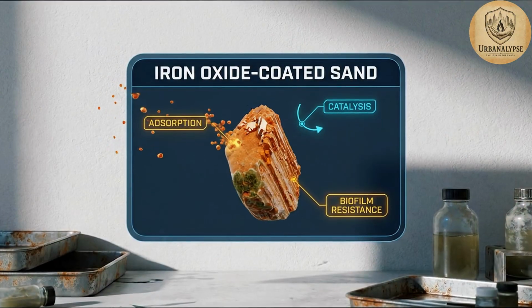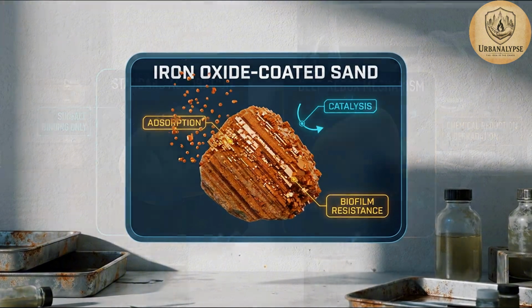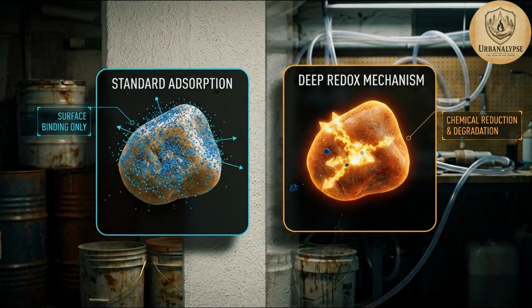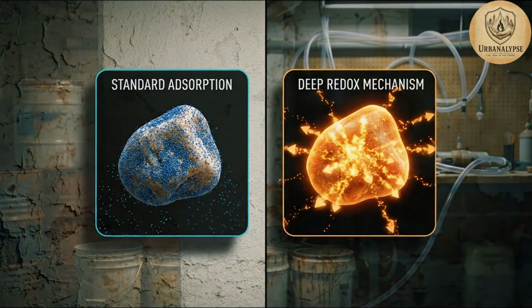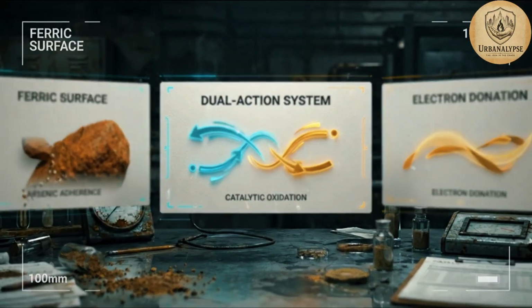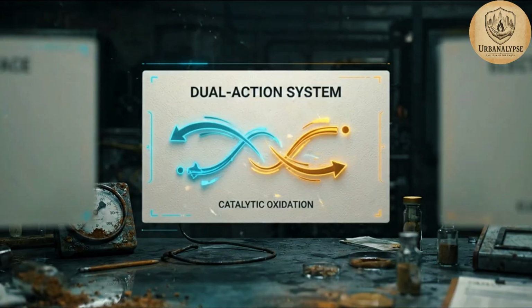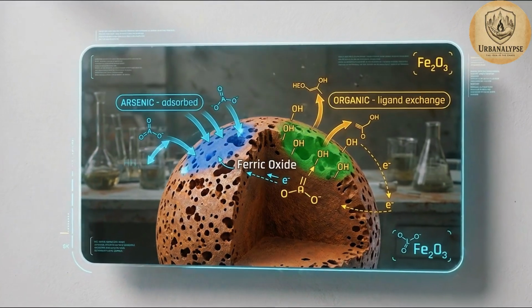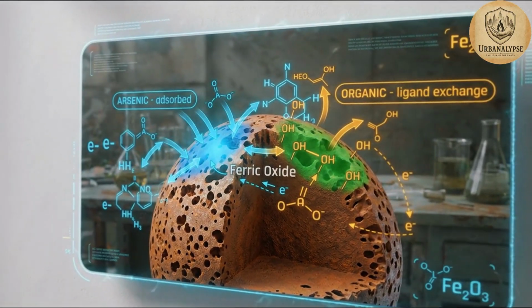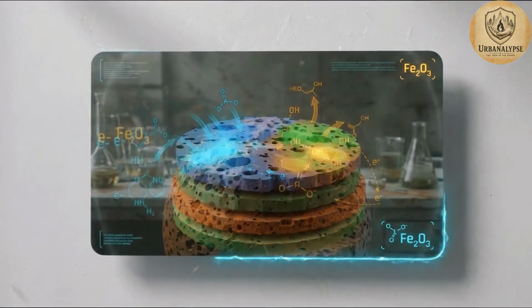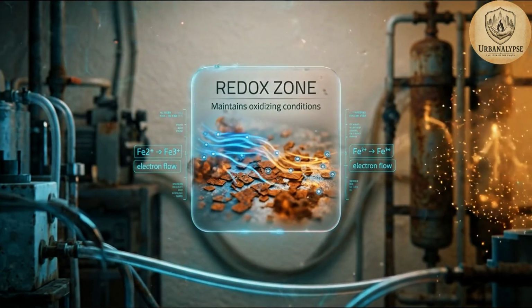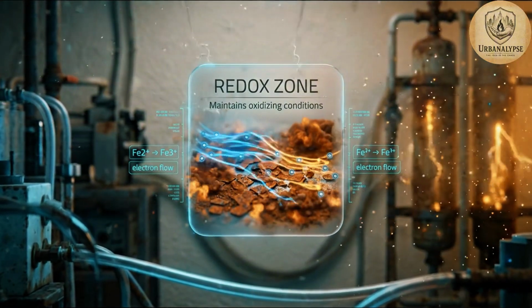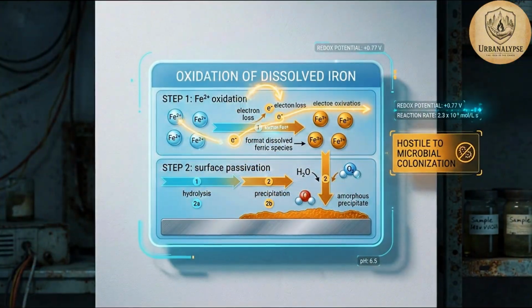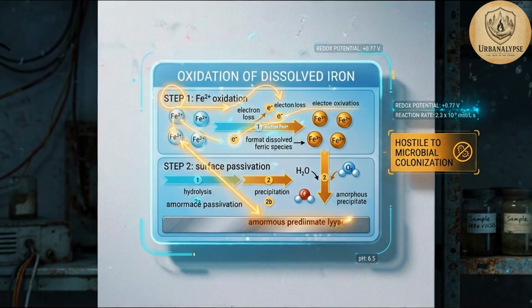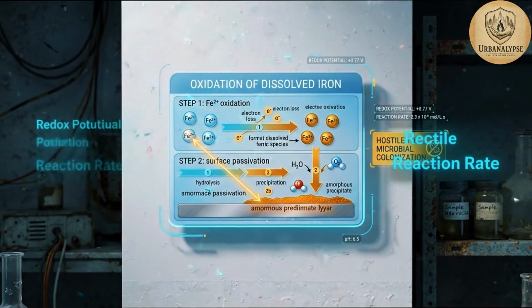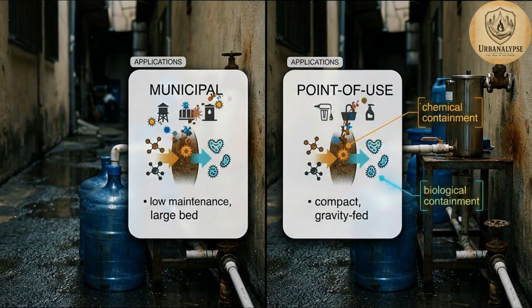Iron oxide-coated sand filters. The first time I pulled apart the literature on this, I kept reading it as a standard adsorption medium. The mechanism runs deeper than that. Iron oxide-coated sand is a dual-action system. The ferric oxide surface adsorbs arsenic and certain organic compounds through electrostatic and ligand exchange mechanisms. That's the part most descriptions cover. What they underemphasize is that this same surface creates a redox environment that catalyzes the oxidation of dissolved iron and maintains conditions hostile to microbial colonization simultaneously.